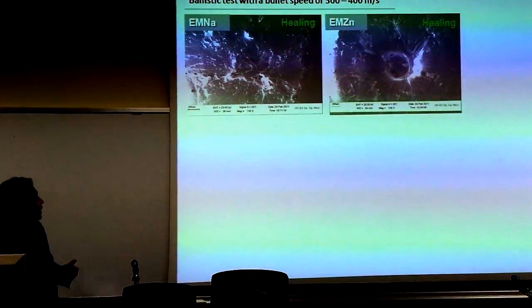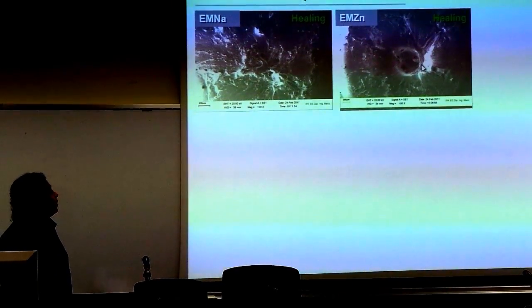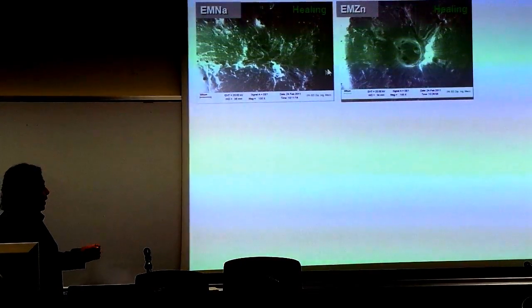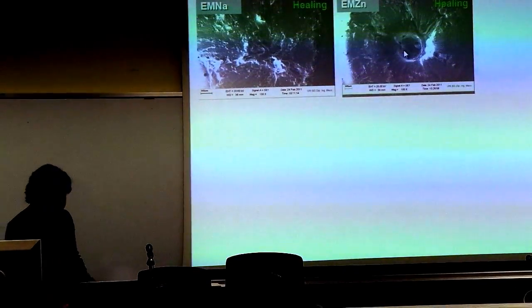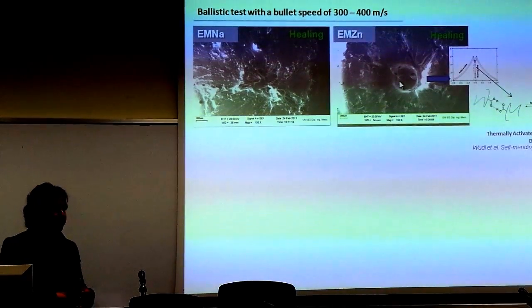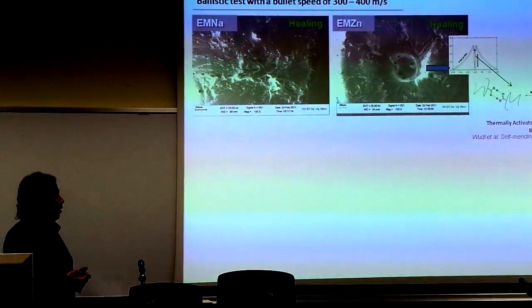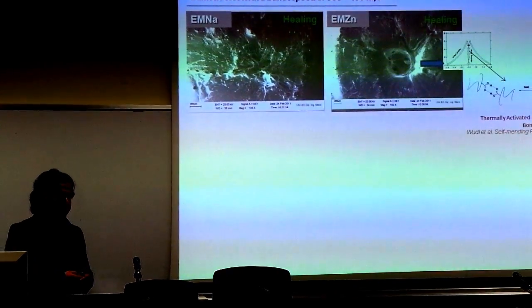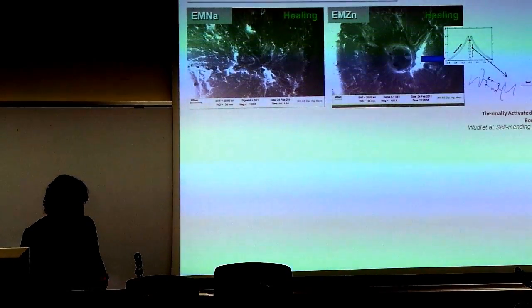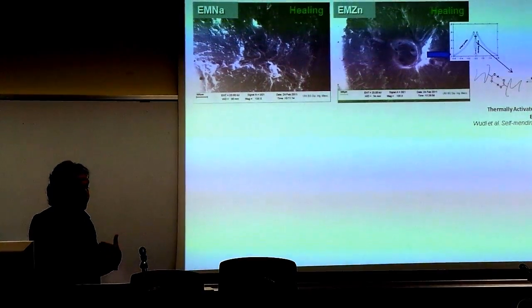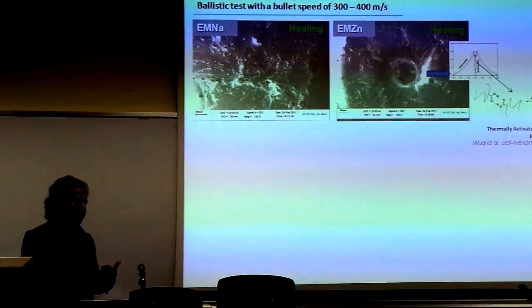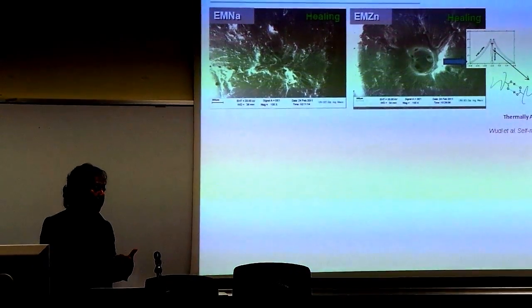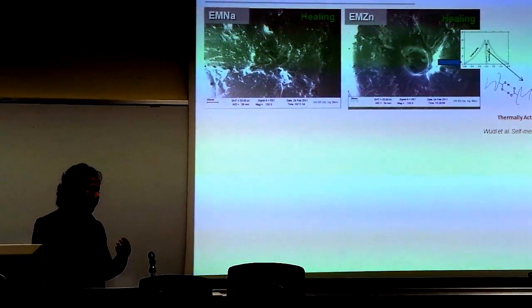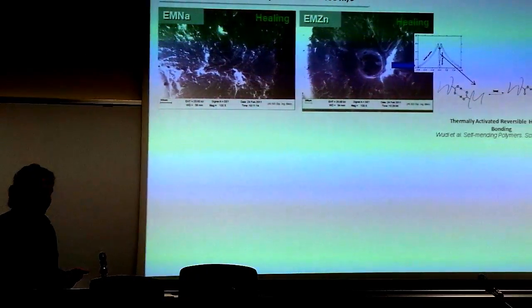And if you take a closer look at the impact zone of both ionomers, although their morphology is different, you can see a complete interdiffusion and melt flow behavior at the impact zone, which is further supported by thermally activated hydrogen bonding that leads to a complete self-healing in the impact zone. I tried to study further how to evaluate the self-healing ability of ionomers, and I tried to investigate what physical parameters can limit their self-healing ability.